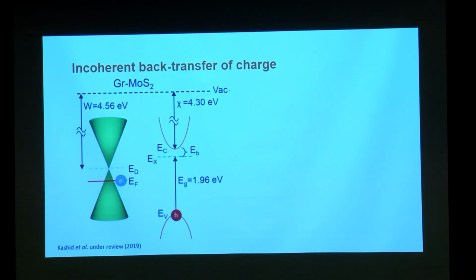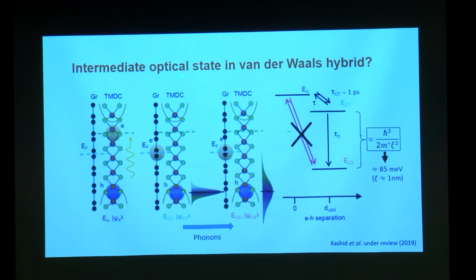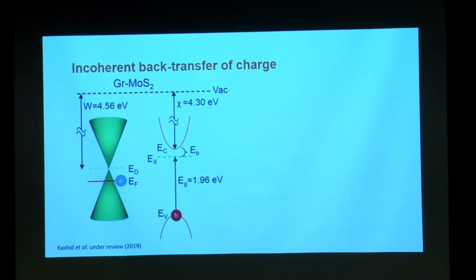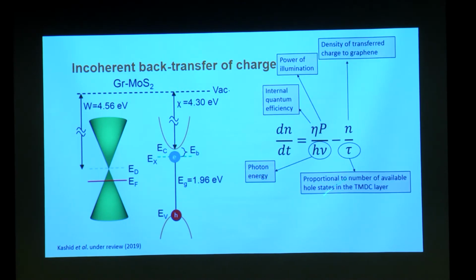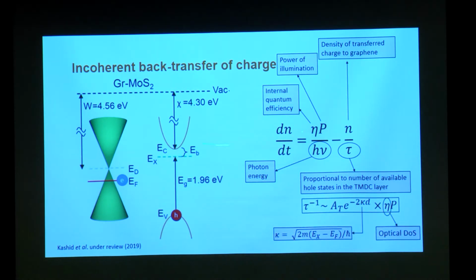So there are two possibilities here. One possibility is that this particular state can now send some electron back into the excitonic state, exactly like what happened in the organic solar cells. I can have what you call an incoherent back transfer of charge. That means now this particular graphene is accumulating electrons by two processes. One is you dissociate the exciton here, and the electrons have come, which is given by the number of electrons formed in the graphene after dissociation of the exciton, minus the amount of charge that is going back, which is given by a rate.